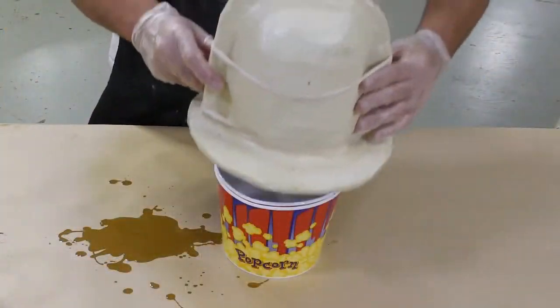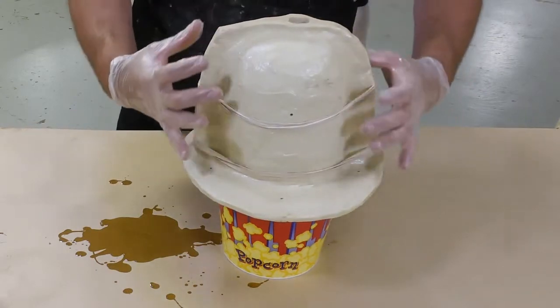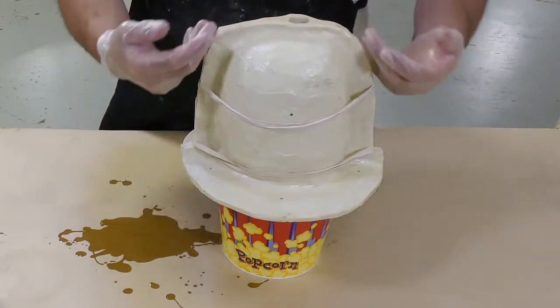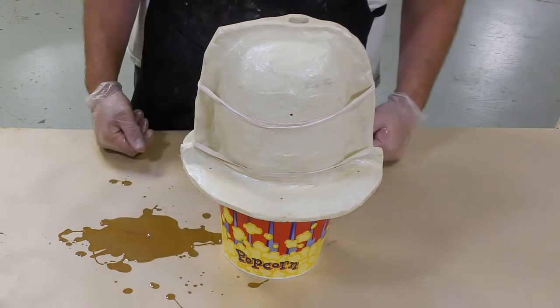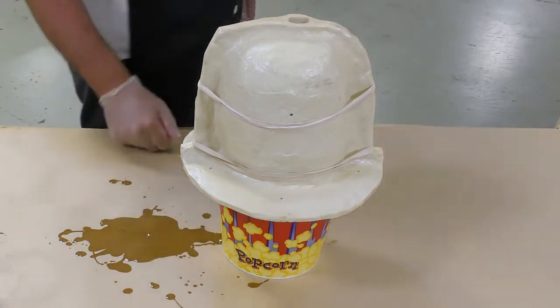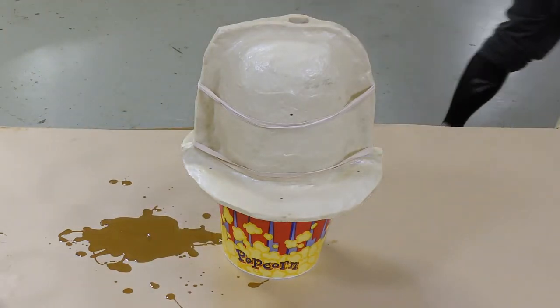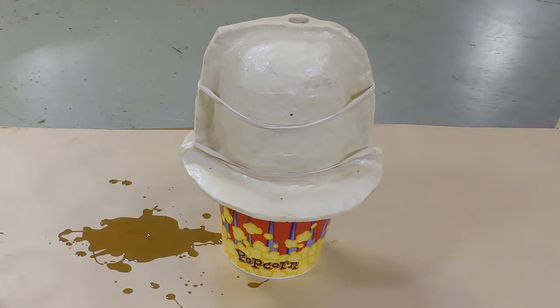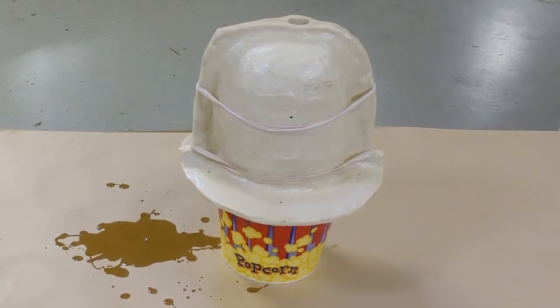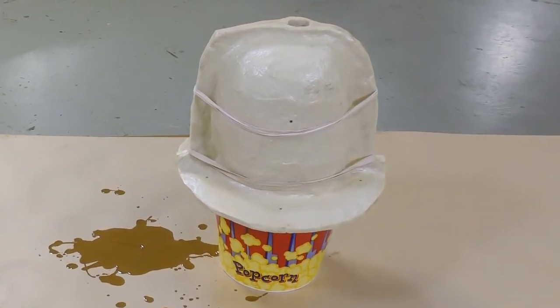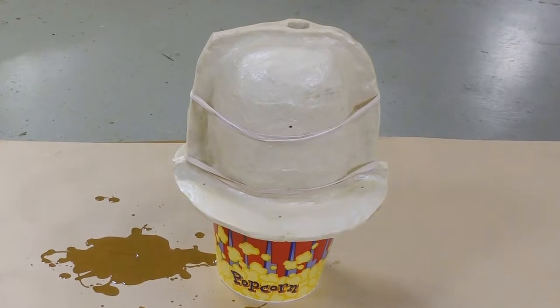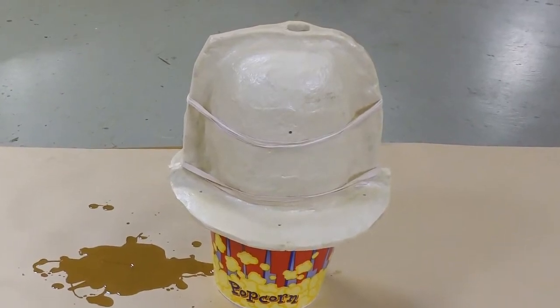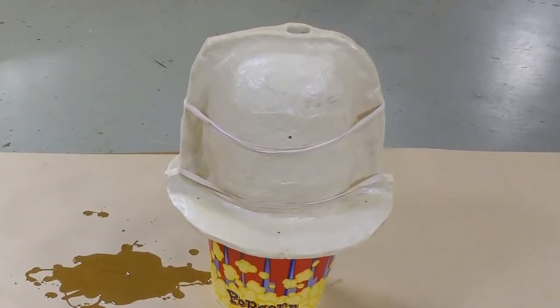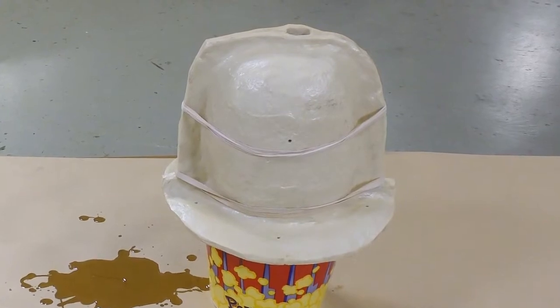After the material has stopped moving, we're going to put the mold upside down like this, just in case any of the material is still moving, it doesn't end up slumping to the top of our casting or the top of the head, rather down and out of the mold. This will minimize the chance of creating a thickened area at the bottom or the top of the head of our casting. We're going to allow the material partial cure for 30 minutes before applying the next layer.